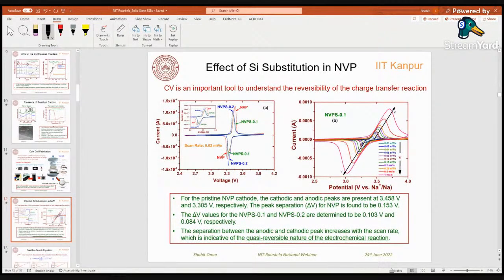Let us talk about the electrochemistry involved in this type of coin cell. First, what we did was to measure the cyclic voltammetry of these half cells. If you look at NVP, NVPS 0.1 and 0.2, this is your cathodic peak and this is your anodic peak. There is a difference between the cathodic peak and anodic peak. You can see that the peak separation for NVP is around 0.153 volts, while for NVPS 0.1 and 0.2 it is 0.103 and 0.084, which means there are more polarization losses involved in NVP compared to NVPS 0.1 and 0.2.